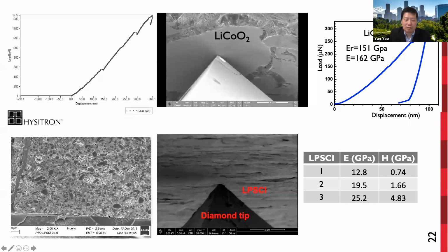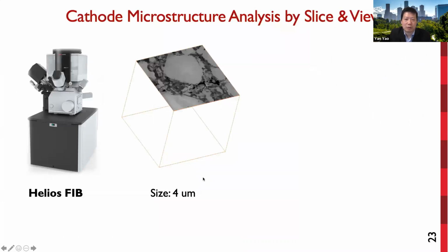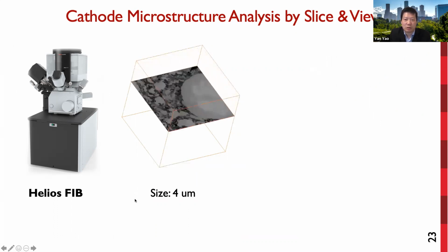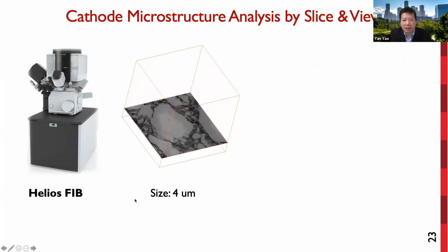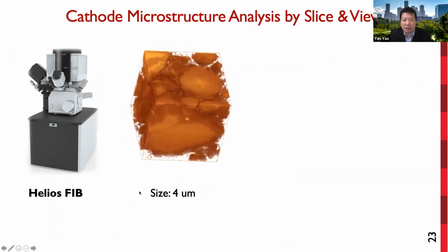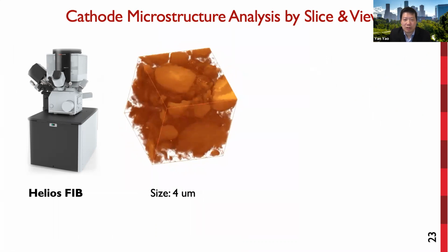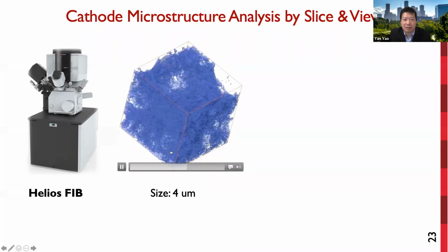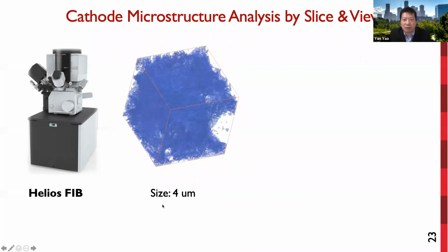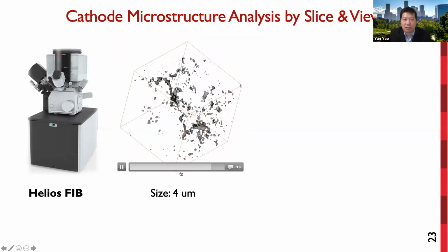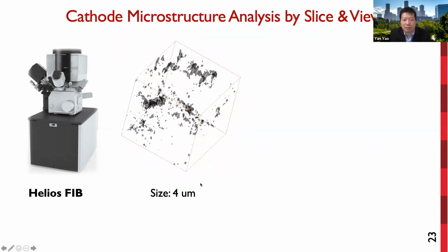to separate and differentiate the cathode versus electrolyte, and even to measure the mechanics of the interface. So finally, we are also equipped with a focused ion beam SEM using the slice and view function. It can enable a reconstruction of the cathode composite. In this example is a PTO LPS freeze mill sample. We can resolve the network of electrolyte. This is the PTO cathode, and we can also see the pore connectivity structure in the cathode composite.